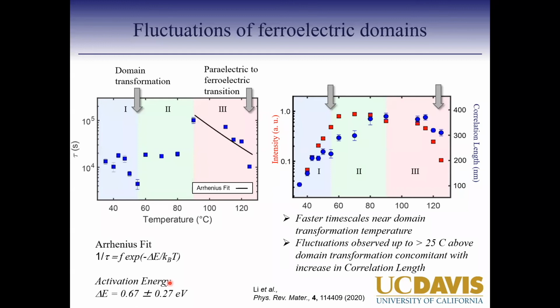So this has been a sort of point of contention. The order parameter of the transition in these systems is the polarization. In bulk barium titanate, polarization changes as a function of temperature in a discontinuous manner, so it's a first order transition. But in a thin film, this transition actually is a second order transition.